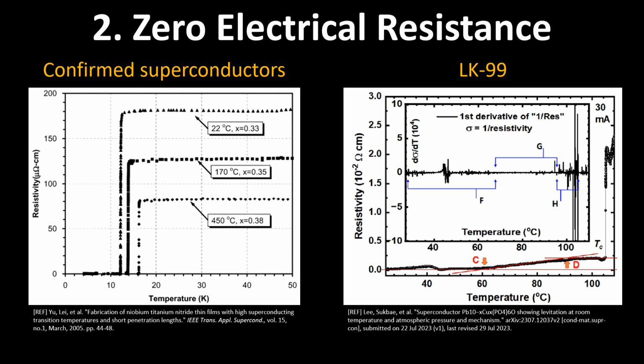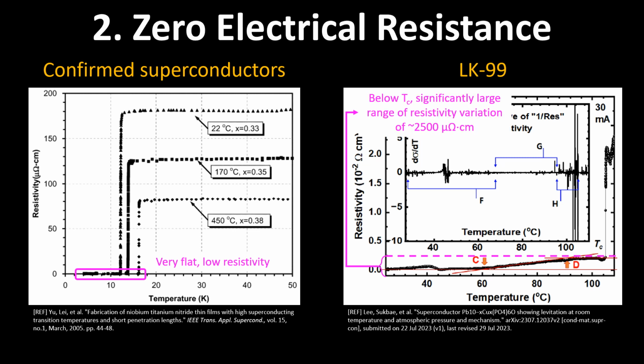As shown in the picture on the left, superconductors, where superconductivity has been previously confirmed, show a characteristic close to zero electrical resistance below the critical temperature. However, LK-99 not only shows a much higher resistance than zero below the critical temperature, but it also appears to demonstrate the characteristic of decreasing resistance as the temperature decreases, as the evident slope shows, which is a behavior commonly found in normal conductors. Thus, it seems difficult to claim that LK-99 is a superconductor with near zero electrical resistance based on the resistance data presented in the arXiv paper. For more explicit proof, verification through repeated experiments and rigorous data analysis seems necessary.